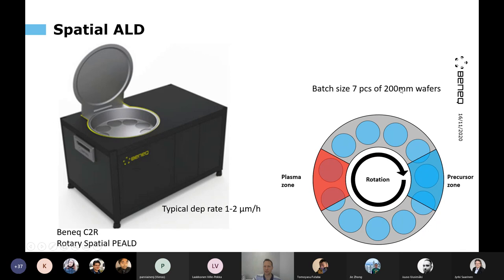But the drawback is that now the batch size is smaller, so it's just kind of one plane, so we can't stack things on top of each other anymore. But in this system, the C2R system from Beneq, batch size is maximum 7 pieces of 200 millimeter wafers. So that gives you an idea of the batch size.